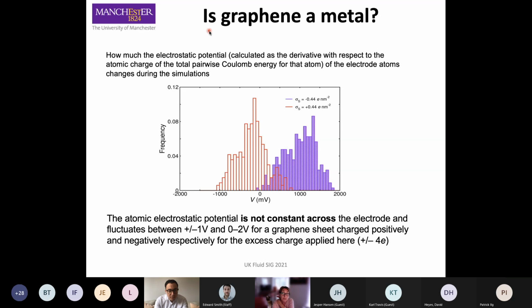Then, because we have the full quantum mechanics of the graphene, what we could look at was also what happens to the electrostatic potential. So we could actually see if graphene changes its electronic properties, basically. So one point was to see if graphene changed from a semi-metal to a metal behavior when ions approach the surface. This was suggested from some DFT calculation. So what we did, we calculated the electrostatic potential on the graphene atoms, so the electrode atoms, when the graphene is negatively and positively charged. So if the graphene is a metal, what we should see is that basically all the atoms have basically the same electrostatic